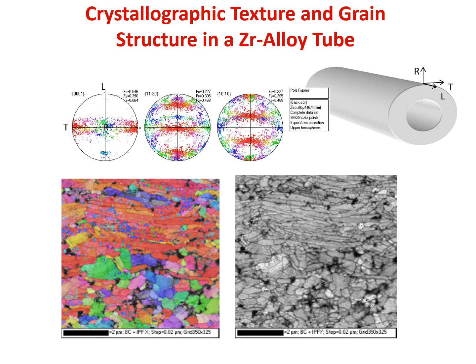So basically the orientation of a grain in a given structure can be obtained by collecting the Kikuchi maps, those orientation maps that I showed you earlier, for each individual grain, and then matching up the orientation obtained from an SEM with a grain, and plotting that on a pole figure, as you see here.